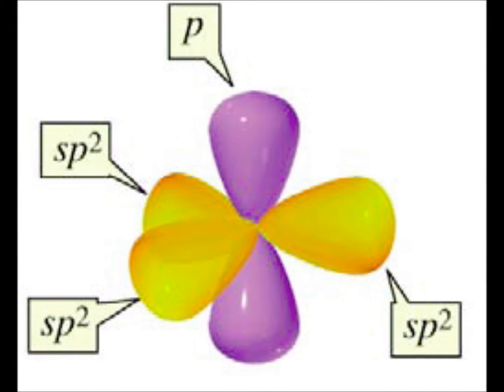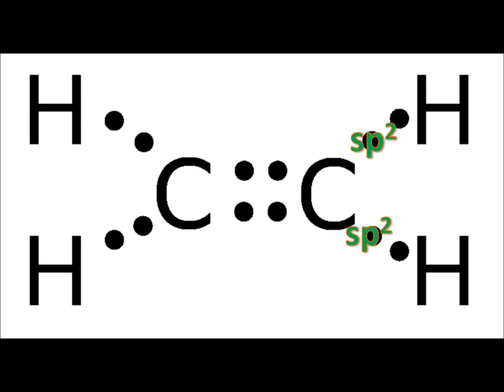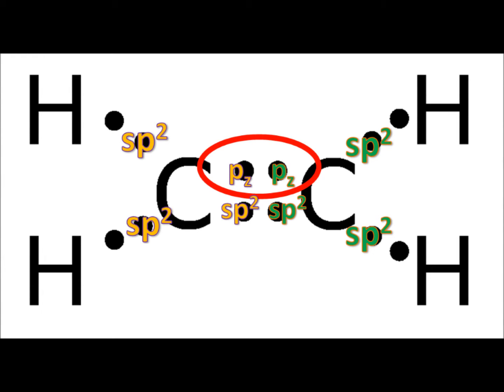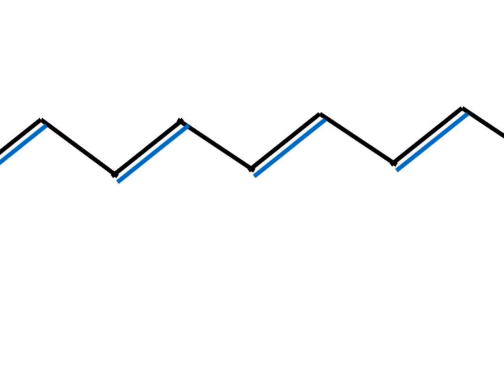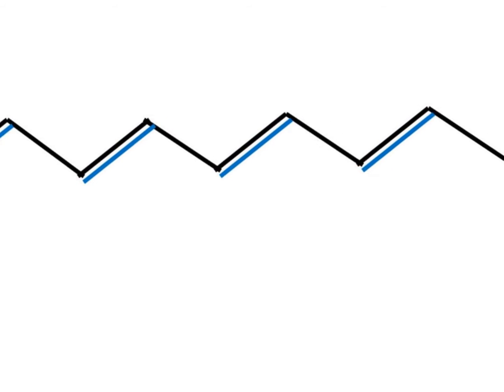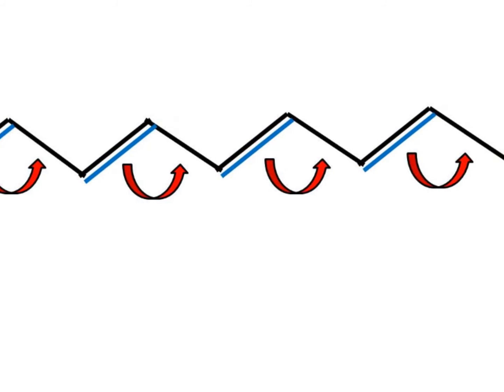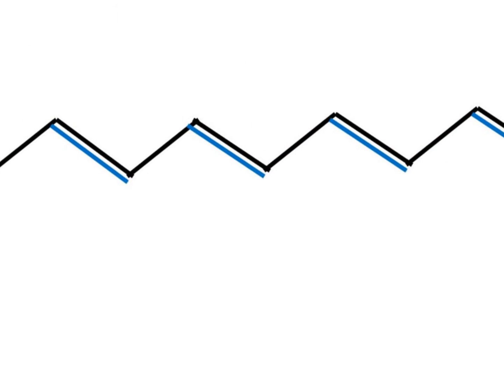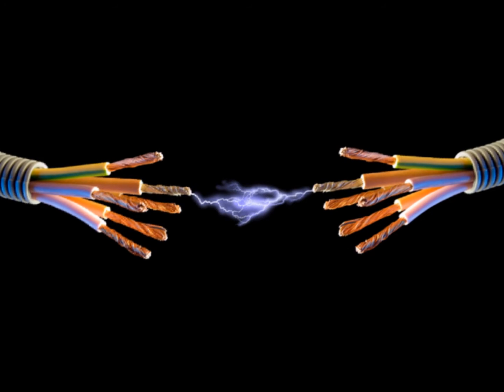However, if instead of the four sp3 orbitals we now have three electrons in sp2 orbitals and one electron in the unhybridised pz orbital, we see a different arrangement of bonds. As before, each of the electrons in a hybridised orbital forms a single covalent bond, but the electron in the pz orbital of each carbon can form a second bond between them. This gives a chain of alternate single and double bonds, which are called conjugated double bonds. The electrons in a double bond are much less tightly bound and so are more available to move. This is called the mesomeric effect, where the electron density in a molecule can be redistributed through the movement of electrons, and this can only arise in molecules that have conjugated bonds — and it is these mobile electrons which cause current to flow.